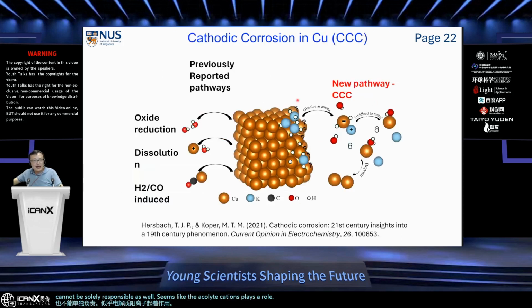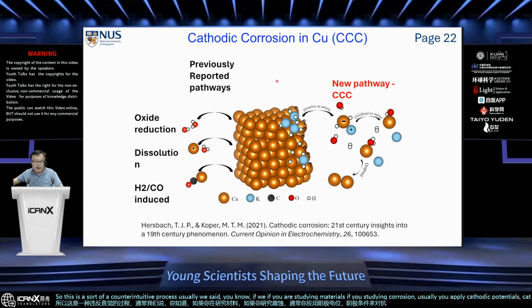So that reminds us of a classic electrochemical phenomenon called cathodic corrosion. This is a counterintuitive process. Usually, if you are studying materials, if you're studying corrosion, you apply cathodic potentials, cathodic conditions, to fight against corrosion, cathodic protection against corrosion. But in this case, if the condition is right, if you have alkali metal cations in the electrolyte at deep enough cathodic conditions, you will actually trigger a new mechanism to cause copper to reconstruct.